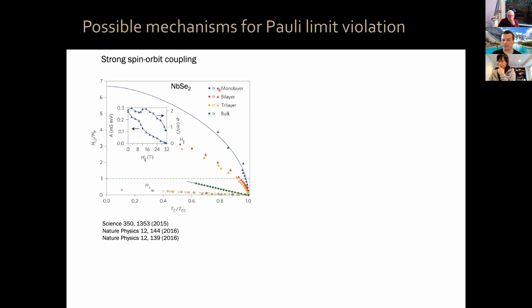If you take monolayer niobium diselenide and you apply an in-plane field, you can see that the Pauli limit, which is this dashed line, gets violated by a lot. That's because you have very strong spin-orbit coupling in niobium selenide. You have this Ising type superconductivity where your Cooper pairs are locked by a 1,000 Tesla spin-orbit induced magnetic field, which means you have to apply a lot of in-plane magnetic field to do anything, okay?